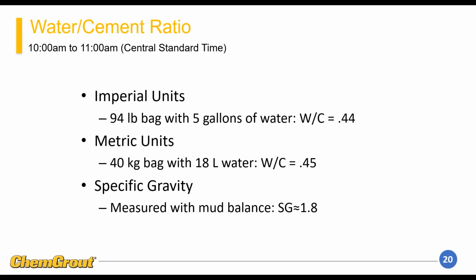The next thing is the water to cement ratios. So we can mix the water and cement in different ratios to achieve different strengths. A very common water to cement ratio is 94 pounds of cement to 5 gallons of water, which will give us a water to cement ratio of 0.44. And then we also show some of the metric units. When we do mix this up, one of the main quality control tests is the specific gravity, which is measured with a mud balance. And for the 94 pounds of cement with 5 gallons of water, the typical mud balance reading, specific gravity reading, will be 1.8.